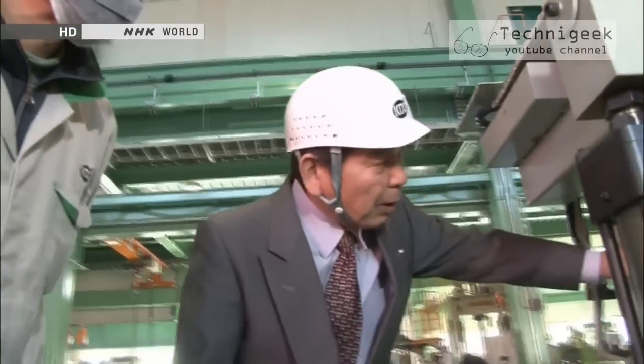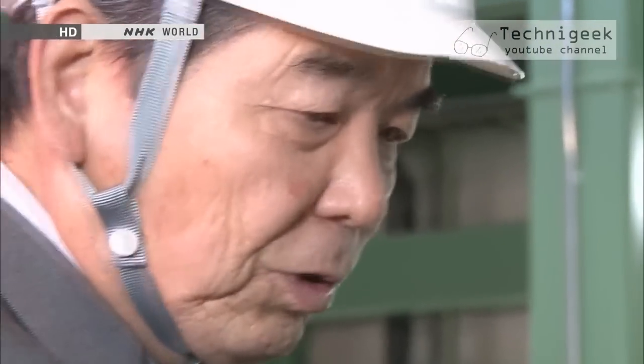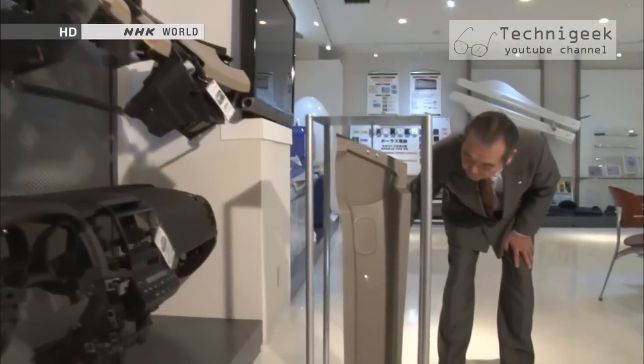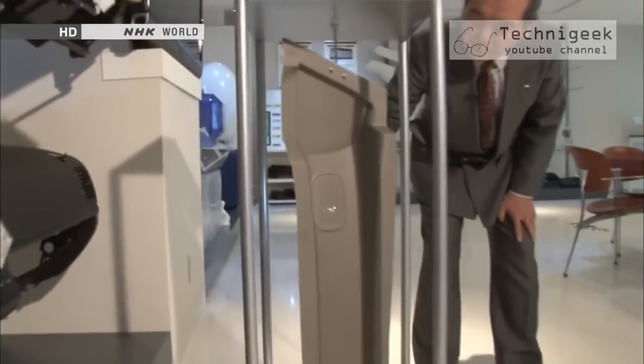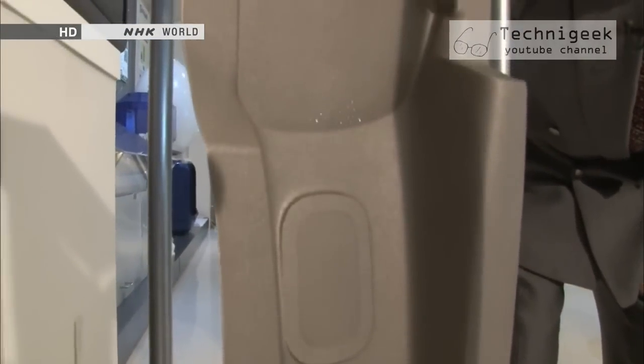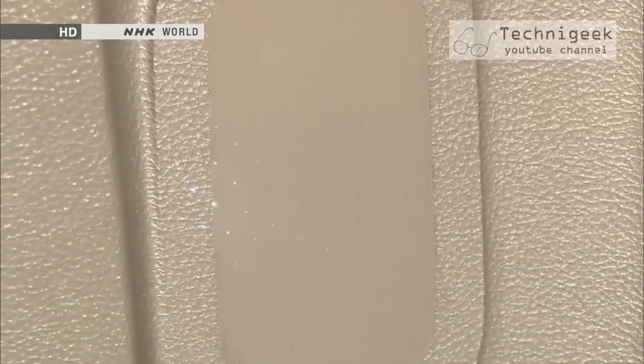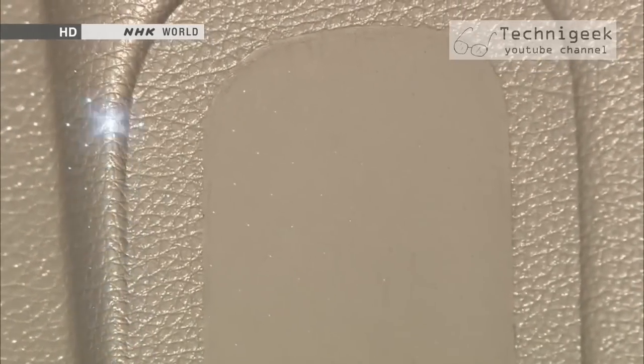So the Takumi thought of a way to vacuum-seal the area of contact between the resin and the mold. But how could he pump out the air while at the same time reproducing the patterns? He and one of his employees spent two years on research and came up with the idea of making tiny holes 0.1 millimeter in diameter all over the mold. It created a better air vacuum and therefore better adhesion, and resulted in superb pattern reproduction.